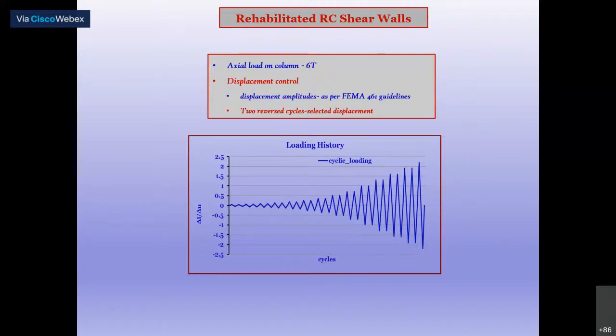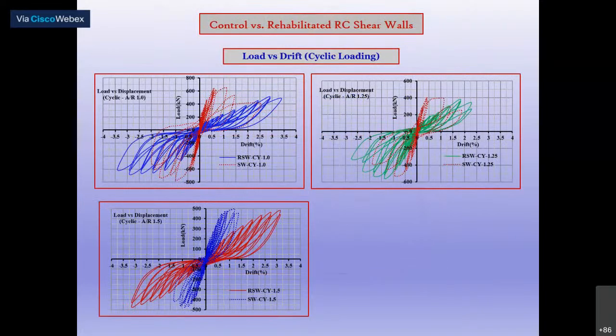We continued up to failure. We found that the conventional retrofitting was advantageous. That means there was a good improvement, the capacity slightly improved, and the ductility too, but soft failures were observed, and there was a significant decrement in the stiffness. This is the response: these are the original and these are the repaired specimens. So there are more deformations, slightly reducing.